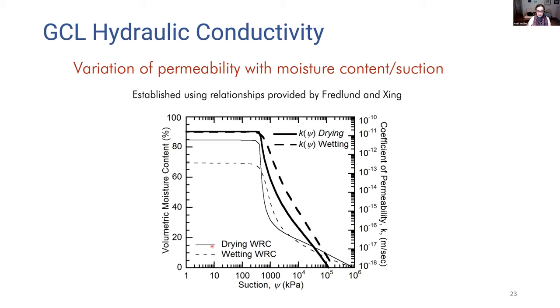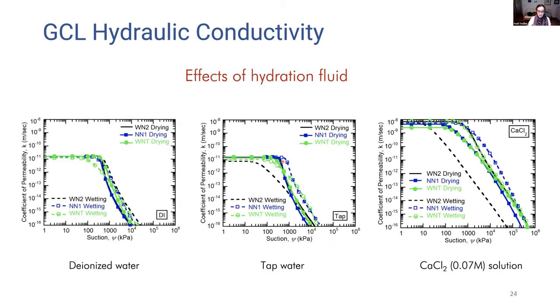The thinner lines are the drying and wetting, hydration and dehydration, moisture suction relationships, the kinds of relationships that we were looking at in the earlier slides, and the thicker lines correspond to permeability functions converted from the moisture suction relationships. For both cases, drying curves are shown with the solid line and the wetting relationships are shown with the dotted lines. We did this analysis for all of the materials that we tested in our program. We now have graphics of coefficient of permeability versus suction. Deionized water tests are shown on the left, tap water tests are in the middle, and calcium chloride solution tests are on the right side.